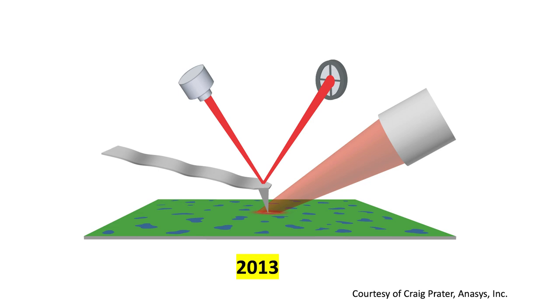The term was first used to denote a method that combined a tunable free electron laser with an atomic force microscope equipped with a sharp probe that measured the local absorption of infrared light by a sample. It required that the sample be coupled to an infrared transparent prism and be less than 1 micron thick. It improved the spatial resolution of photothermal AFM-based techniques from microns to about 100 nanometers.